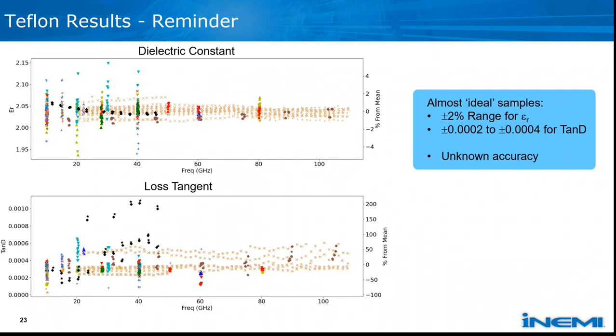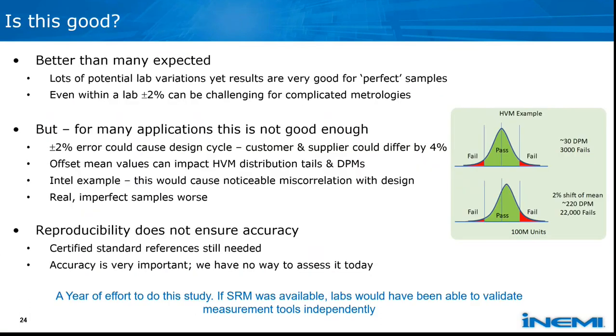In this case, I think it's a little bit worse, maybe plus or minus 3 or 4%, mostly because I think the Teflon thickness had more variation than the COP materials. But again, the message is the same: if you want a precision result in terms of dielectric constant, we just really can't do much better than this today, because we have no reference standard with which to all agree upon a true value.